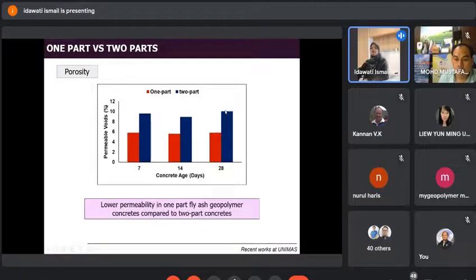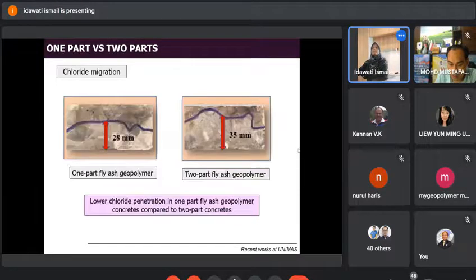So for fly ash geopolymer concrete, basically what we found is that the voids are around 7, 8, 9, 10%. But when we did a one part system, we found that the permeable voids or the porosity is much lower, almost half of the two parts. So this is a good indication that the one part system is doable, is comparable, and can be applied. We also compared the one part fly ash geopolymer system when it comes to its chloride penetration. Like you saw just now, our fly ash geopolymer has quite deep chloride penetration, but it is worse in the two part, okay, compared to one part. This is also NaOH pellets, one part system.